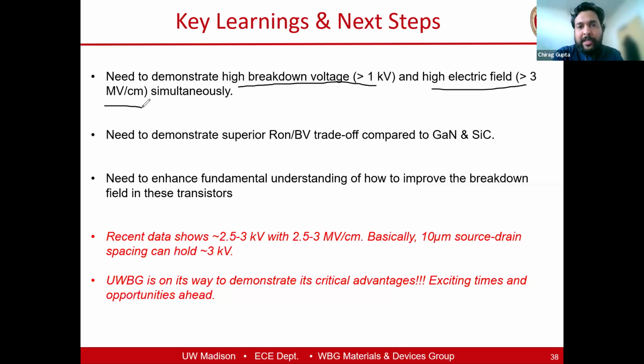So there is still a need to demonstrate a superior on-resistance breakdown voltage trade-off. And one of the key things is to enhance our fundamental understanding of how we go from there. Getting close to 1.5 megavolt per centimeter is not that challenging. We were able to achieve it rather easily, and other folks as well. However, pushing that number to higher E-field is proving to be non-trivial, especially if you want to go to 1.5, 2 kilovolt, 2.5, 3 kilovolt. Below 1 kilovolt, it's a different ball game where you can achieve high field, but once you start to cross 1.5 megavolt per centimeter, we haven't seen enough work.